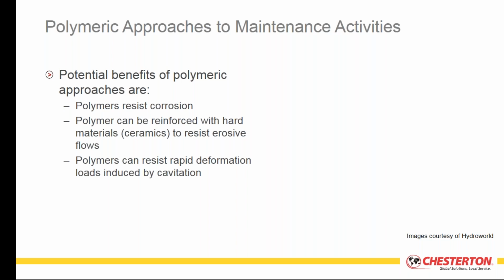Stress corrosion may be more of a problem because, again, you are not addressing the structural aspects of the base metal. All you're doing is putting a surface enhancement on the surface. And cavitation is another area that can be addressed by polymeric coatings, but you're not eliminating the forces of cavitation - you are reducing the effects. You're allowing the coating itself to be the sacrificial material as opposed to the base metal.